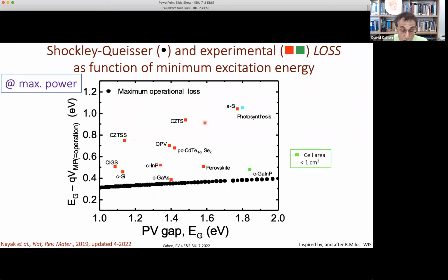And you see it's all over. And there's this disturbing line that suggests that as your band gap goes up, your losses go up. But luckily, there's gallium indium phosphide that saves the day. And here's perovskite. And that's why there's such enormous excitement about perovskite, because it's a relatively new cell that at maximum power, at relatively high band gap, is closer to this theoretical minimum loss that we can't do anything about in a single cell than any of these others.